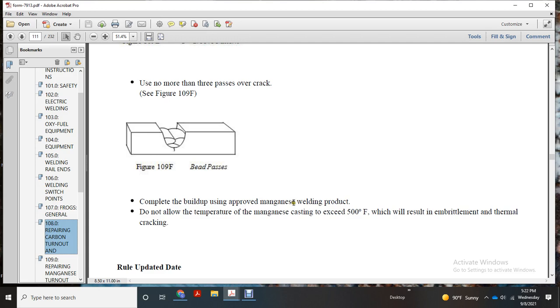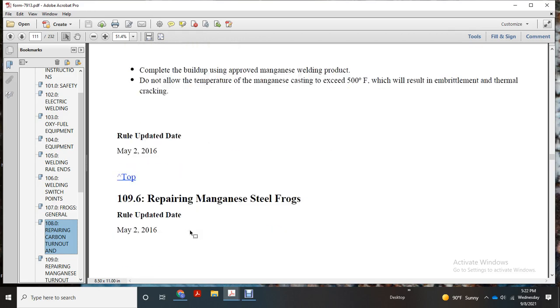Complete the build-up with the approved manganese welding product, ensuring the temperature of the manganese casting does not exceed 500 degrees, which will result in embrittlement and thermal cracking.